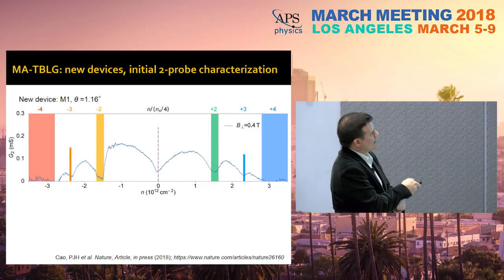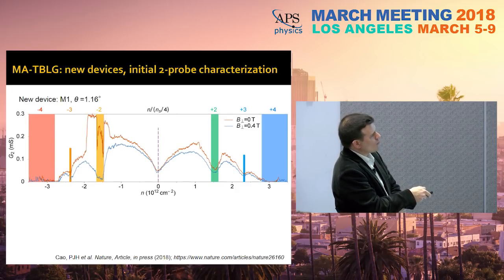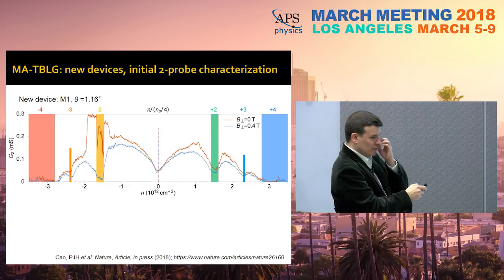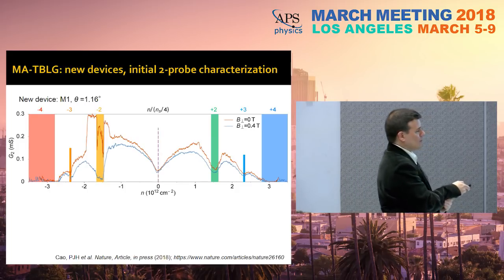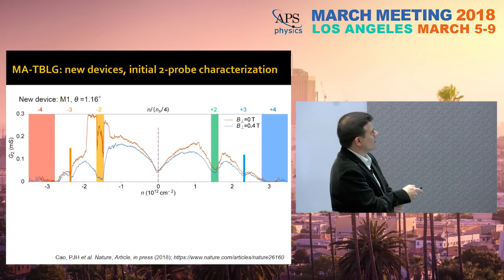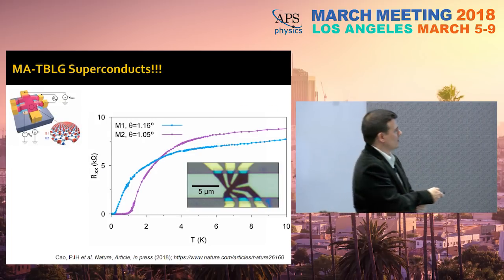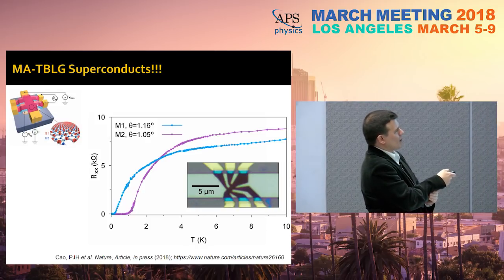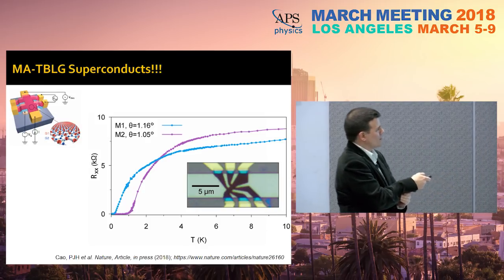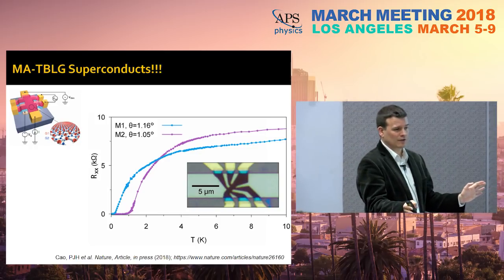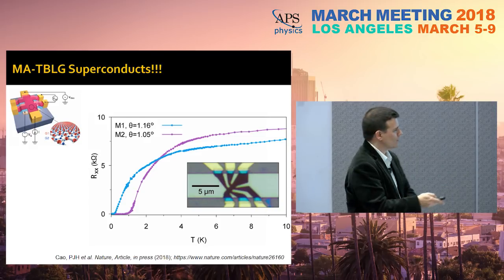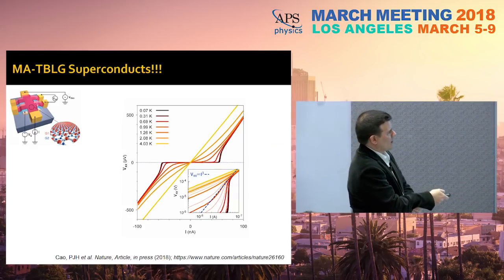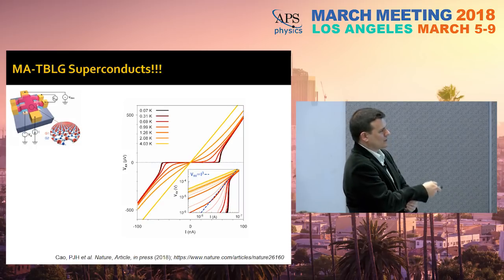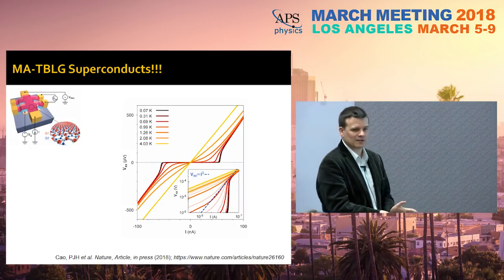Now if we take this trace, again, this is two-terminal, at zero magnetic field, you see that not too much happens here, a little bit, but not too much action. But here there's a dramatic increase of the conductance. This is, again, a two-terminal measurement. If we now take four-terminal measurements, what we get is that these devices superconduct. This is the resistance as a function of temperature. These are two devices, 1.16 degrees and 1.05 degrees. The resistance goes to zero, decreasing by three orders of magnitude below our noise measurement floor. We can also take the VI curves at low temperatures. These are absolutely flat. We can do a standard test of 2D superconductivity. This thing very much superconducts.